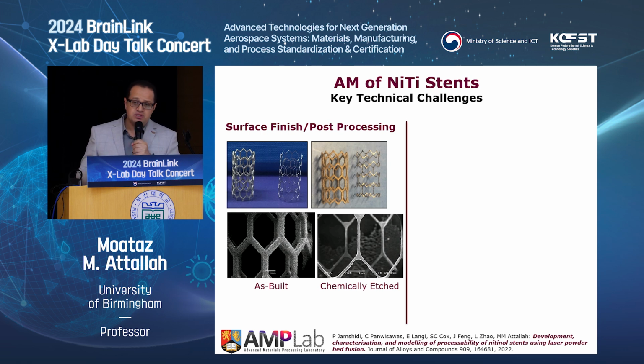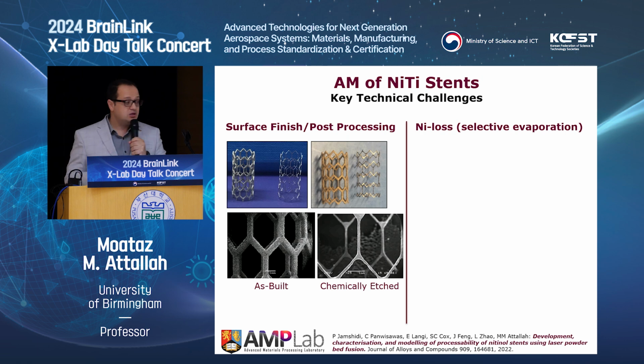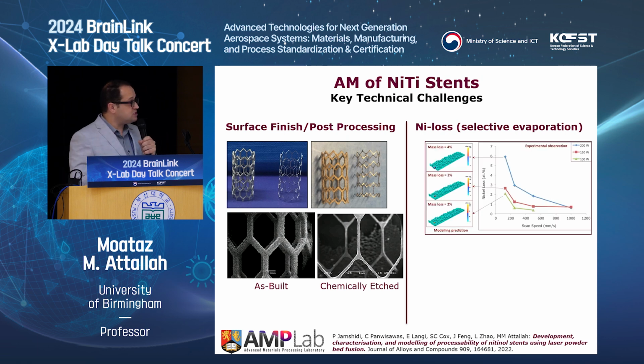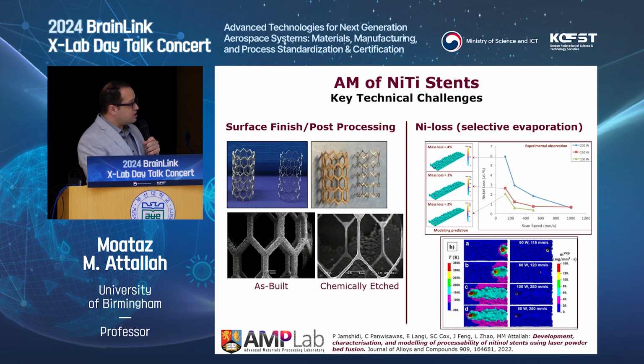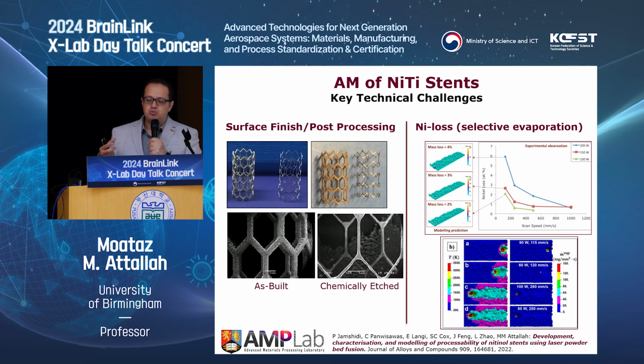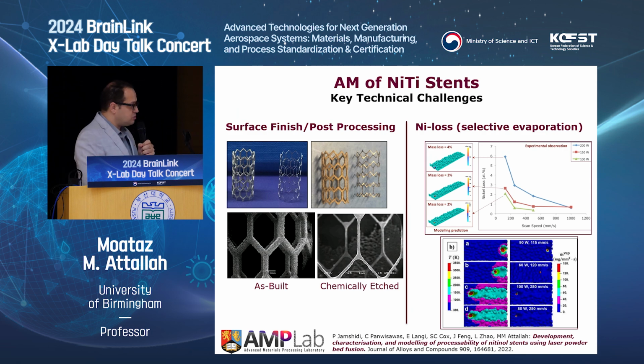The other key problem that we had was that if you try to print nitinol, which is meant to be 50-50 nickel titanium, you end up getting some nickel evaporation. Nickel will selectively evaporate. So we worked with our colleagues at Oxford University back then to simulate the effect of the process parameters on the evaporation, so you know roughly what scan speed and laser power will generate how much nickel evaporation. We simulated that by computational fluid dynamics. As an outcome, we know how much nickel is being lost, and we can add more into the alloy at the start. So instead of printing 50-50 nickel titanium, we print 55 nickel, 45 titanium, to account for the loss of nickel during the process.